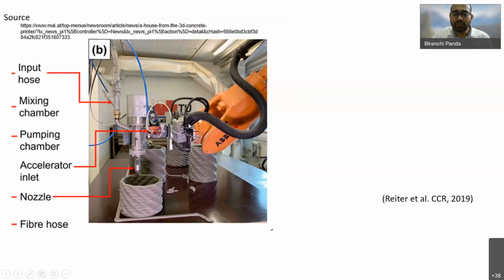There are some solutions where people are using microwave at the nozzle to immediately cure the concrete so that you can deposit more layers. There are some solutions where they are trying to add some chemical so that this material is going to be quickly hardened after it is deposited. So there are many solutions to increase the hardening rate of the concrete that is being deposited, so that you can put more layers.